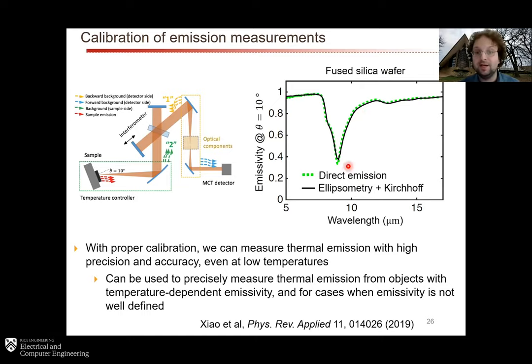And then the solid line is very, very careful spectroscopic ellipsometry, plus the application of Kirchhoff's law, which you can do easily in this case, but it's more difficult in other cases. And you can see that they line up almost exactly. So we're very confident that we can have vanishingly small error bars on our emissivity measurements at this point, which has enabled us to do a lot of things, some of which I'll show you in just a second.